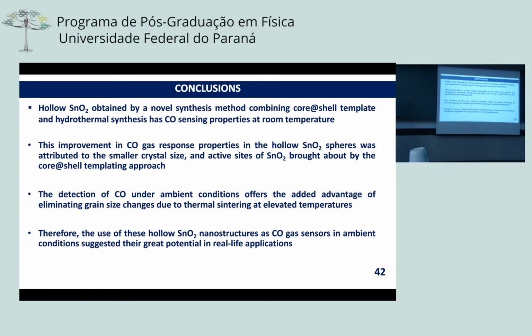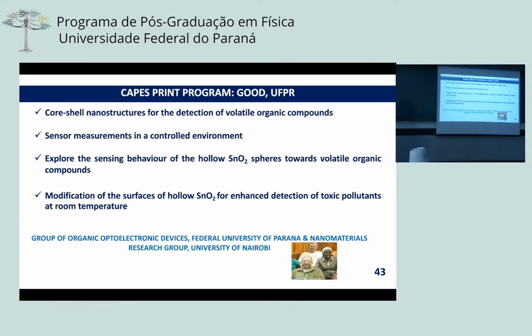And the detection of CO under ambient condition offers the added advantage because now we don't have to worry about thermosintering that occurs at higher temperatures. And the possibility of using these materials shows this potential to improve it. So probably by looking at the size dynamics or other properties, we can be able to tune these for room temperature detection of other things.